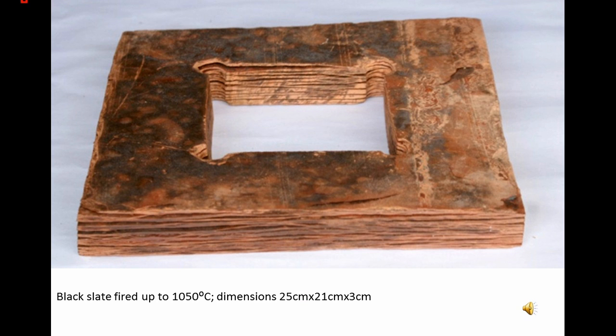Free pyroplastic expansion of slate. Slate behavior, when submitted to high temperatures, exposes some variation, because slate does not always have the same composition or a similar structure; however, there is a strong degree of proximity in most results. When black slate is submitted to temperatures over 1050 C, expansion takes place and the overlapping fine structural blades, proper of this type of rock, become separated from each other, but without being individualized. It means that, in the case of a parallelepiped shape, the opposed faces that are parallel to lamination will not exhibit significant changes of area, whereas the 4 other faces, perpendicular to lamination, increase in area up to 4 times.